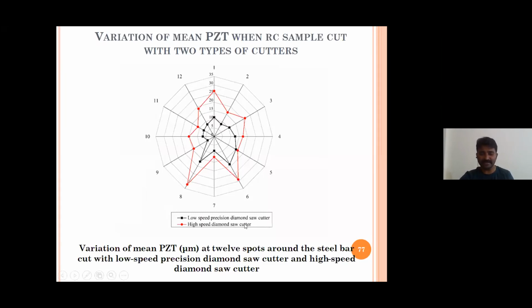As we use high speed diamond saw cutter, there is some damage to the steel concrete interface properties, that is the porous zone thickness. The porous zone thickness is increasing, we are unintentionally increasing it by using the high speed diamond saw cutter. That means we are not able to find the accurate measurement. By using the low speed diamond saw cutter, we could measure a little more accurately. I'm not saying that it is perfect. We still have to find a perfect method to find out without cutting that material, right?